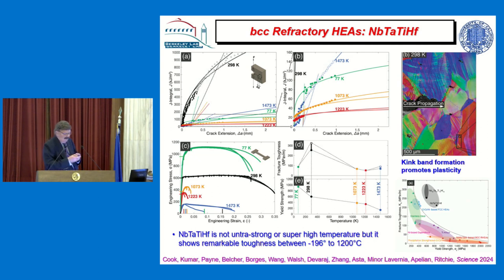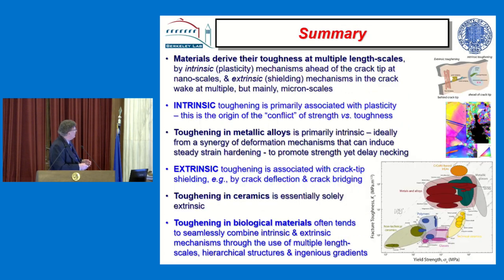No one's really seen much about kink bands, and there are dislocations that get together and cause the material to kink. So they generate a lot of strain, and this has been very effective for toughness. So this alloy doesn't have the very high temperature properties we'd like, but it has remarkable toughness for a body-centered cubic material. So let me finish by saying I've looked at various different ways you can generate resistance to fracture.